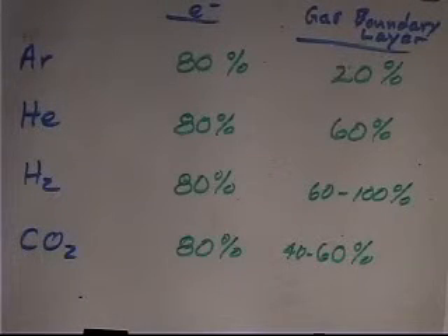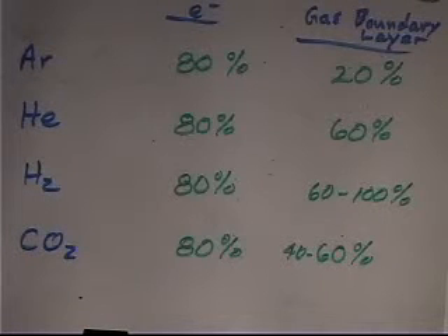Now, I told you, even today, if you go to the welding handbook that was just published 4 or 5 years ago, and you look under the physics of welding, it will tell you that it is the difference in ionization potential between helium and argon that causes helium to have better heat transfer, because that will give you a higher temperature plasma. Except I just explained to you, it's a metal vapor plasma, so it's irrelevant whether you're using argon or helium.